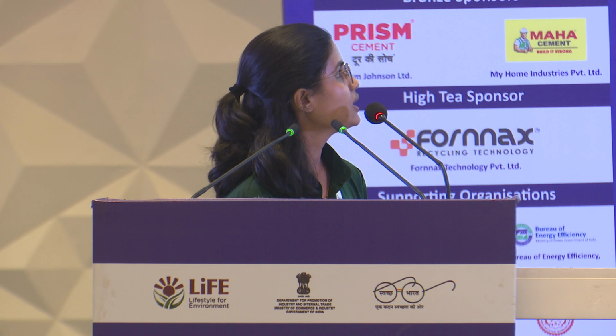The major challenges regarding the commercial production and the wider acceptance include obviously the lack of standards, and other than this, the long-term performance of the cement as a standalone cement is also being researched, and another main factor is the high manufacturing cost. If you look at the raw materials used for its production, it is limestone, bauxite, and calcium sulfate. And if you look at the major oxide composition, it has reduced calcium oxide and higher alumina demand in the raw materials. The higher alumina demand leads to reliance on bauxite as the major alumina source, which will obviously increase the cost of manufacture.